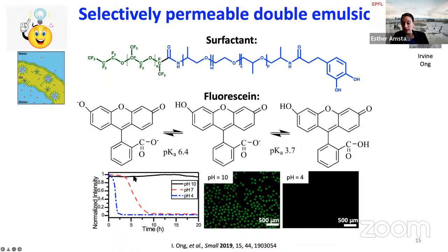If the pH is like 10, where these hydroxy groups are deprotonated, the surfactant is negatively charged. And the fluorescein is deprotonated as well, so it's negatively charged as well. The two molecules repel each other. We basically had no transport whatsoever for a very long time. By contrast, if we lowered the pH such that the surfactants were neutral, uncharged, and some of the fluorescein was charged, some uncharged, we got the transport, and the transport was even higher at pH 4, where both molecules were uncharged. So this to me indicated that the charge, or the attraction between the two molecules, the encapsulants and the surfactants, somehow influences this transport.